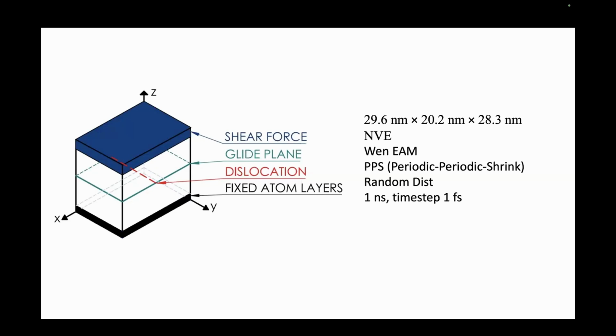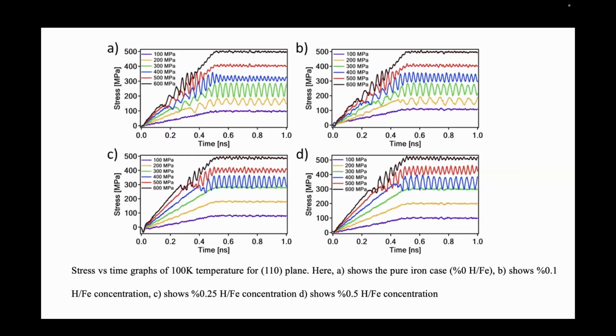We use periodic and shrink-wrapped boundary conditions. Hydrogen distribution is random. Of course, you can do grand canonical Monte Carlo and put a more realistic hydrogen concentration at the core, like we heard from the professor. But for this study, we perform random distribution. The whole simulation time is 1 nanosecond, and the time step is 1 femtosecond. I think it's a sufficient time step because we also monitor the energy and it becomes steady. If the energy is steady, your time step is just fine.